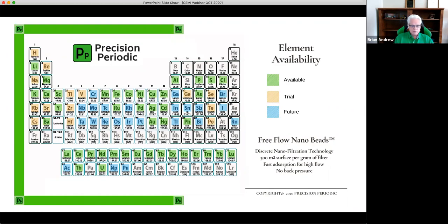All the entire rare earth family, as you see, thorium, uranium, we started with that. The gold is the gold here in the middle of the table. That is a filter where we're not too precise about what we adsorb. So it's not a particularly precise filter for adsorption. So it gets gold, it gets silver, palladium, platinum, cadmium, zinc, copper, and nickel, but it won't get iron. We've actually made it so it won't absorb iron at all. And so that particular filter becomes powerful when we release it, because we can release the gold specifically to give you pure gold, 99.9 gold chloride out of it, and silver chloride and these other materials. So a fairly general adsorption, but a very particular desorption.